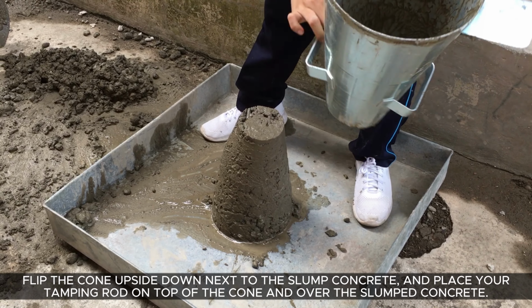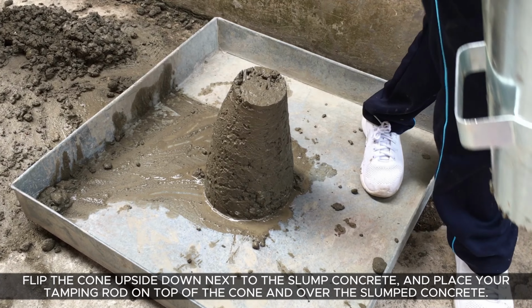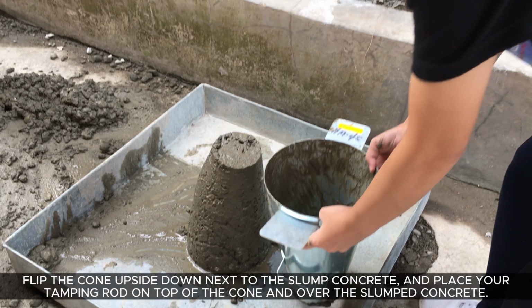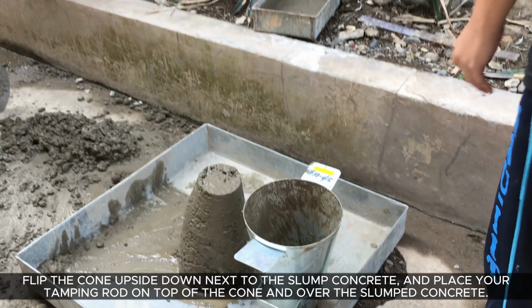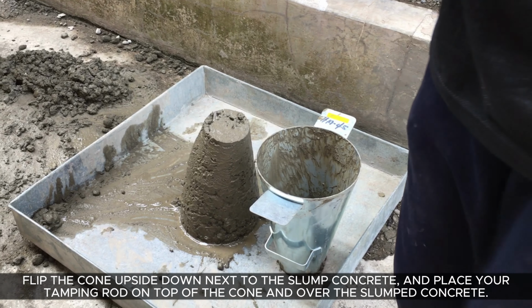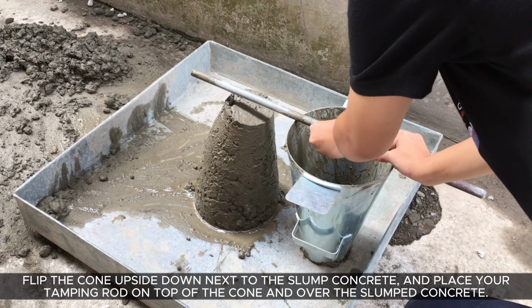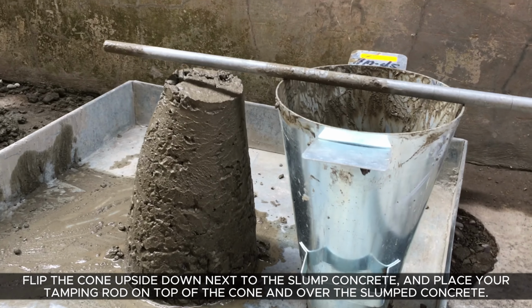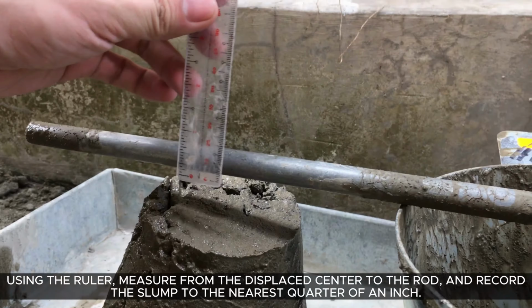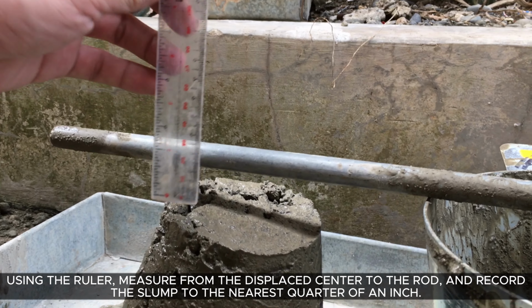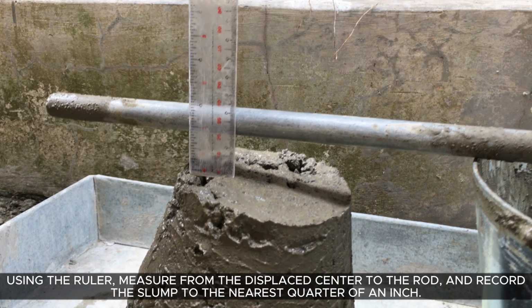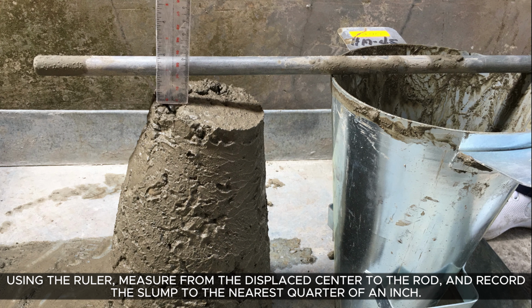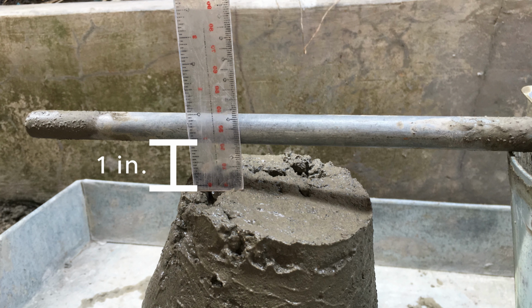Flip the cone upside down next to the slump concrete and place your tamping rod on top of the cone and over the slump concrete. Using the ruler, measure from the displaced center to the rod and record the slump to the nearest quarter of an inch. The entire slump procedure needs to take place in 2.5 minutes. A slump value of 1 inch or 25 mm was obtained in the experiment.